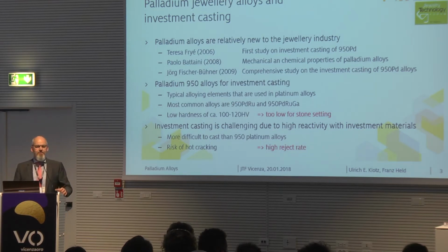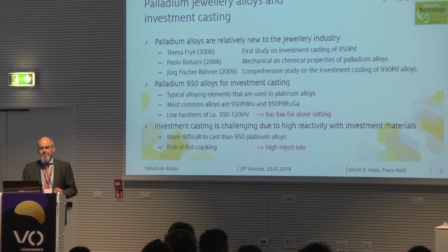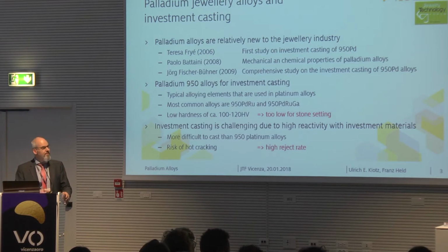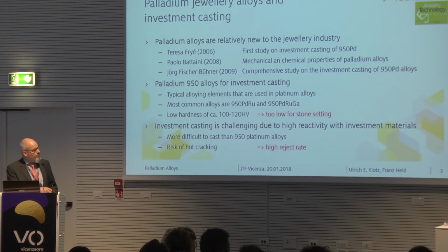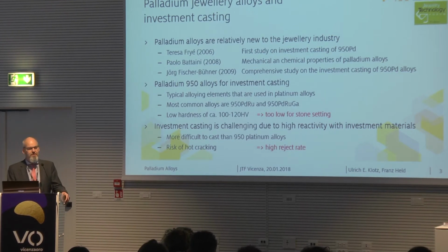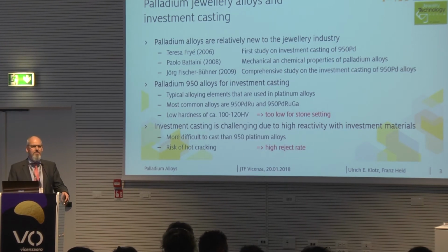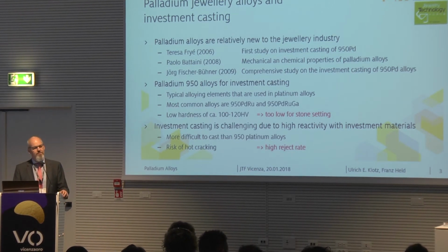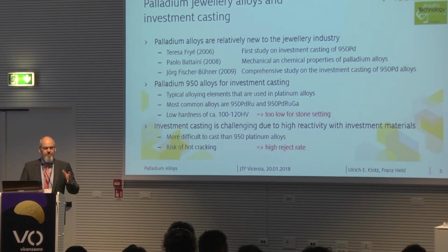Palladium is always standing next to platinum. Platinum is well known and established, but palladium is, as I said, not very well known. One point with palladium is the relatively low hardness. We have a Vickers hardness of only 100 to 120 Vickers, which is a little bit too low for stone setting to hold diamonds or other stones firmly.